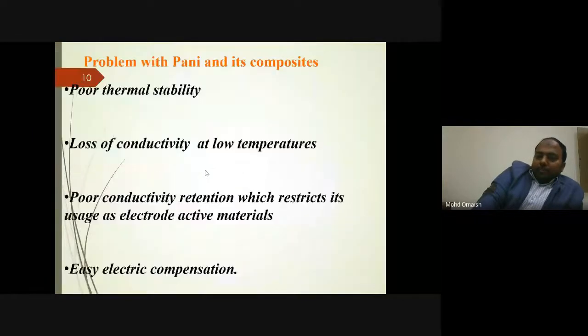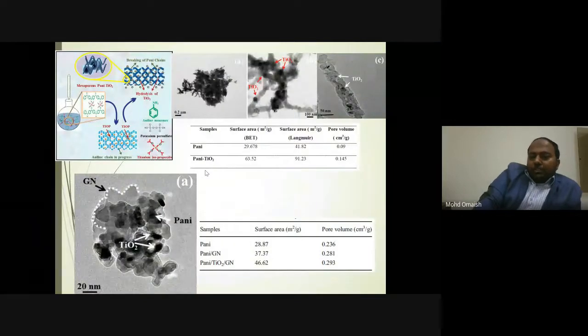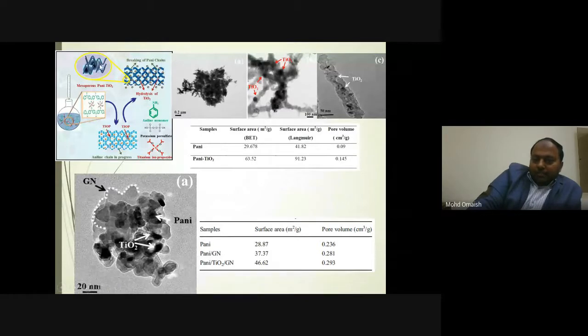Because of that, polyaniline is not used alone. It is used in combination with some metal oxide to impart stability and conductivity. So a lot of composites of polyaniline have been prepared. For example, here we can see a polyaniline titanium dioxide nanocomposite. This is a one-pot synthesis of polyaniline titanium dioxide nanocomposites.